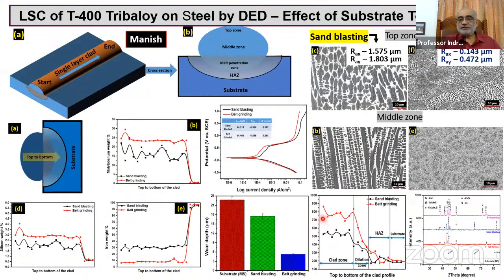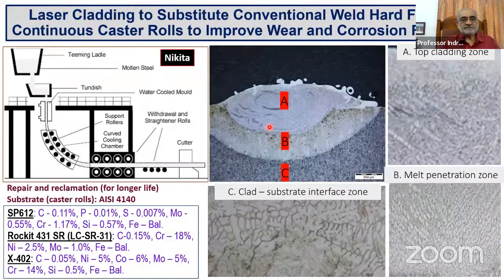As a result, you retain higher hardness, and the phase aggregate also is pretty much the same. By the way, I forgot to tell you that here the cladding is Tribaloy T-400, which is a multi-carbide boride mixture in a martensitic base. They can provide very high wear resistance, and even corrosion resistance, provided you maintain the thickness well. This is from Nikita Mohite.